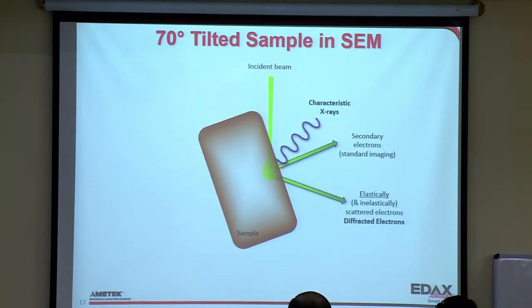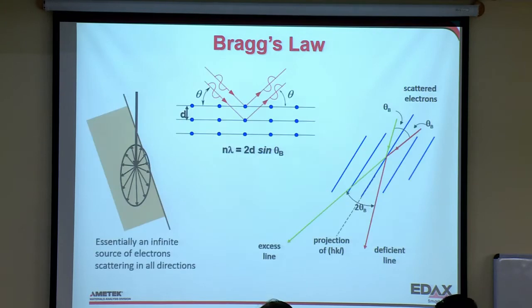And that's because what we have is this interaction volume as the incident beam interacts with the crystal. And you have electrons going out in all directions. So you can think of it almost as an infinite number of electrons in an infinite number of directions. And that's an important concept when it comes to EBSD, and that's because of Bragg's law. As those electrons are coming back out of the sample, they all have different angles. And as they interact with the atomic planes, those that satisfy Bragg's law give us a signal. They give us a coherent diffraction.